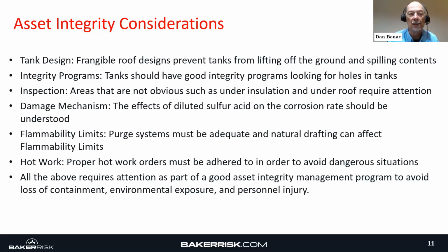This particular tank did not have a robust integrity program, obvious from the corrosion that was evident. There were inspections that were done, but they were inadequate because of corrosion that actually occurred under insulation. Many of you are probably familiar with CUI, corrosion under insulation. As I mentioned, the damage mechanism of diluted sulfuric acid was not fully understood. And although they had a purge system, the purge was inadequate. So you could say, well, I checked that box, we purged it.